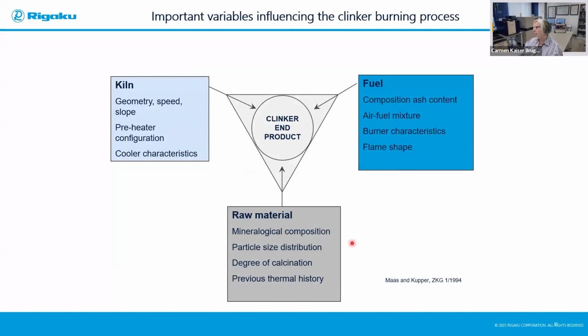But if you look at this diagram, you can see that we have the kiln here, we have the fuel, we have the raw materials. Today we will look at the fuel, how this composition will influence this end product, which will be the clinker. If we look at the kiln, the geometry, the speed and the slope will influence this. The preheater and configuration will influence this. And the cooling characteristics will influence this. Of course, for the raw materials, the mineralogical composition is important. The particle size distribution is important. The degree of calcination, and of course, the thermal history.